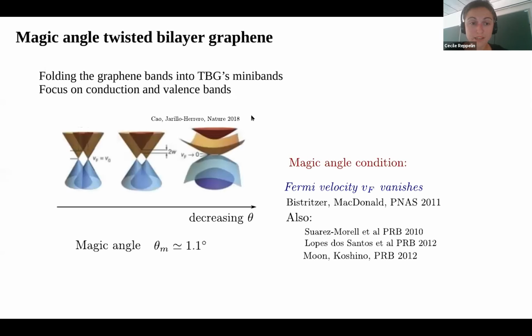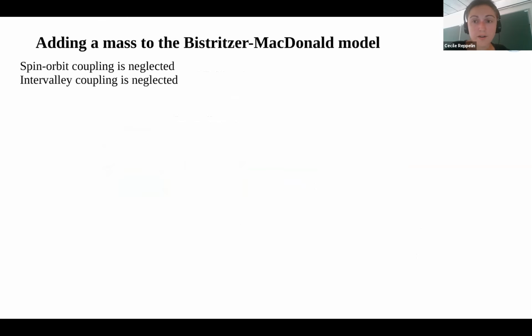So you know the usual story: as you go to very small angle, you flatten the band very much until you reach a magic angle of around 1.1 degrees. Then if you keep going down, the bandwidth will start increasing again. So you will stop at the first magic angle. Now this is where the story differs slightly from the regular magic angle twisted bilayer graphene: we're going to consider magic angle twisted bilayer graphene in the case where it is aligned with its hexagonal boron nitride substrate. So now I'm going to slow down again to treat this part.